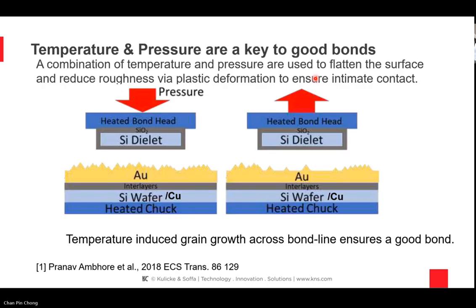We've done a lot of very systematic studies on understanding the effect of pressure and temperature. The principle is actually very simple. When you apply pressure to a rough metal surface, you flatten that surface at the atomic level. When you apply pressure and temperature, as shown here, you're able to achieve very good surfaces over the area of the dielet, which I show on top, so that any protruding surface asperities get flattened completely. And then of course, we have temperature-induced grain growth across the bond line, and this ensures a good bond.